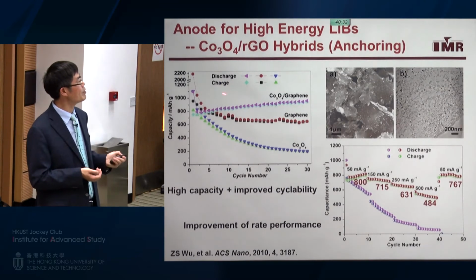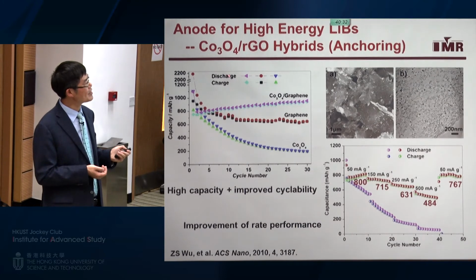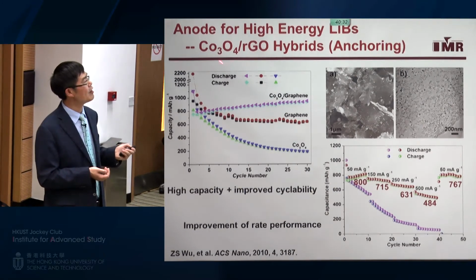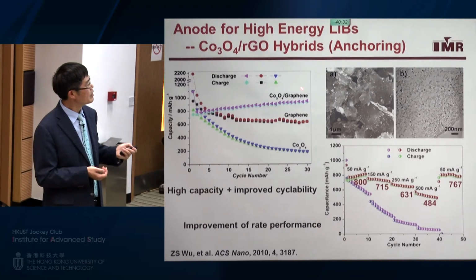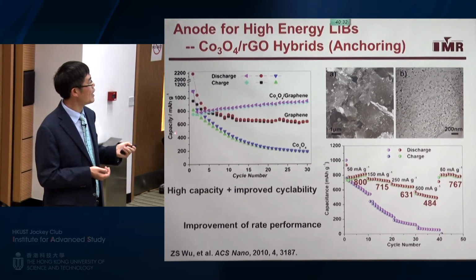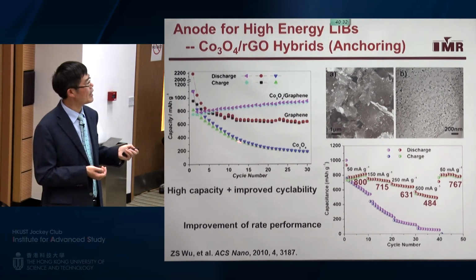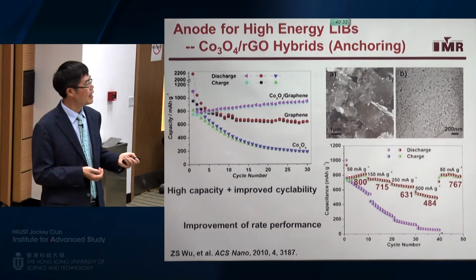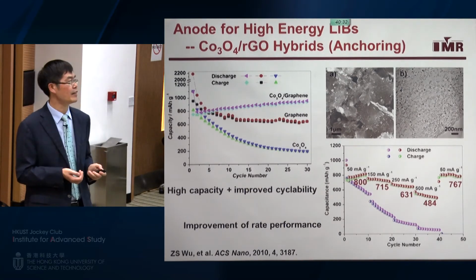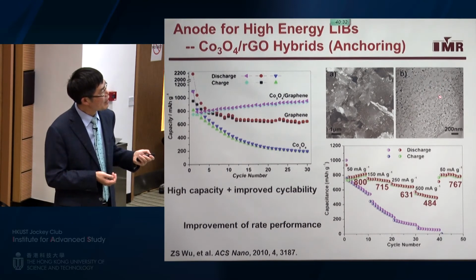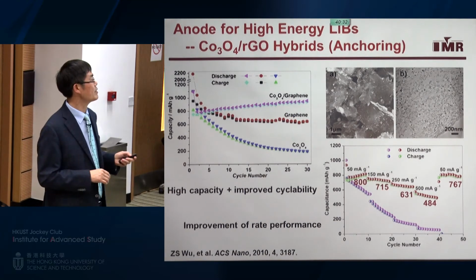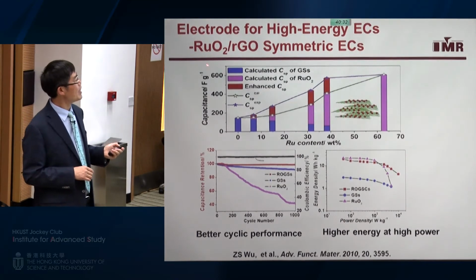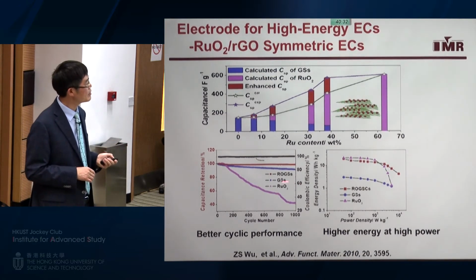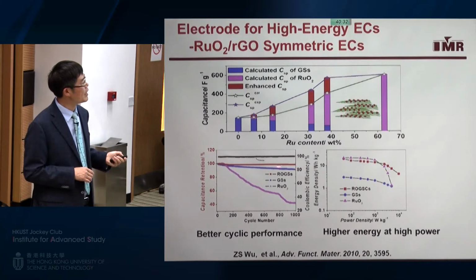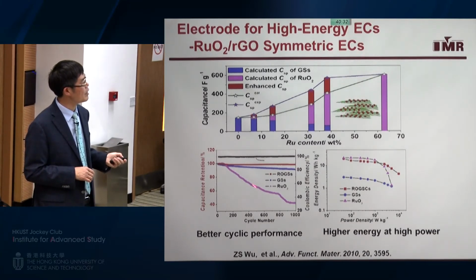So here I gave you two examples. One is cobalt oxide. Probably this is one of the first papers for those kinds of graphene hybrids. As I can show you, those hybrid materials have very good cyclability compared to the pure oxide, and also much better rate performance compared to the pure oxide. So you can say the oxides are nanoparticles on the graphene. And also, we have done ruthenium oxide for supercapacitors. And similarly, we can get very good cyclability compared to the pure ruthenium oxide.